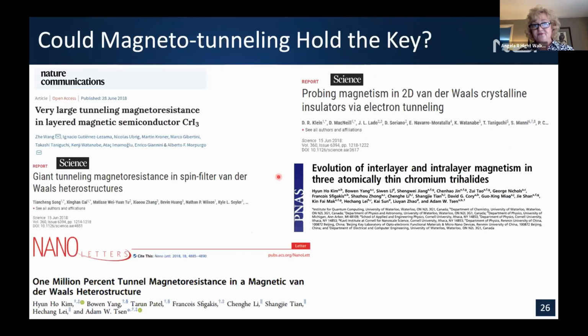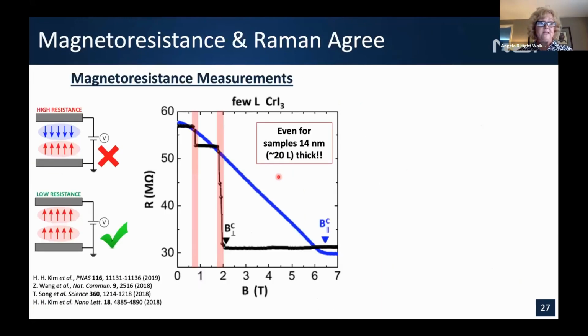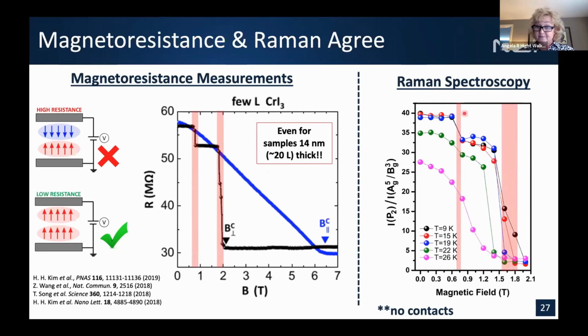So at that time, of course, many of the magneto-tunneling papers were coming out. And we thought, well, perhaps they hold the key to helping us explain what we're seeing with our phonons. Of course, they can see high resistance when it's in the antiferromagnetic configuration, and then low resistance when it's in the ferromagnetic configuration. And what they saw were real step functions at about 0.8 and 2 Tesla. And this particular sample, I believe this is Kin Fai Mak's work, but there were many papers done, was up to 14 nanometers. And we looked at our data, and sure enough, we also saw a bit of a step function close to 0.8 and 2 Tesla.